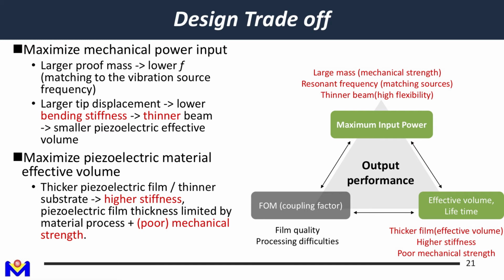Okay, and we can also maximize the piezoelectric material effective volume. So we want a thicker piezoelectric film, but remember it's only working in 3-1 mode. In 3-3 mode with a top electrode, it's not actually effective. So we want a thick piezoelectric film and a thin substrate. This also induces higher stiffness, and higher stiffness means we reduce the tip displacement. Also, the piezoelectric film thickness is somehow limited by different material process that we are going to talk about later. The other factor you have to consider is the poor mechanical strength, which means the beam may break.